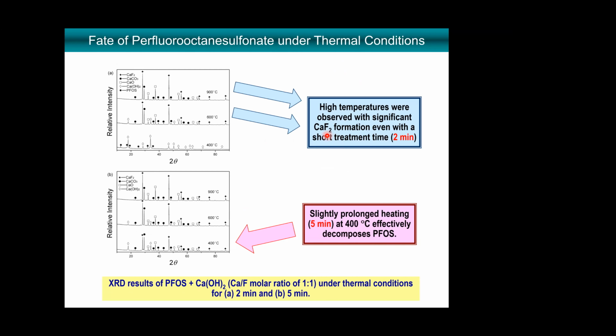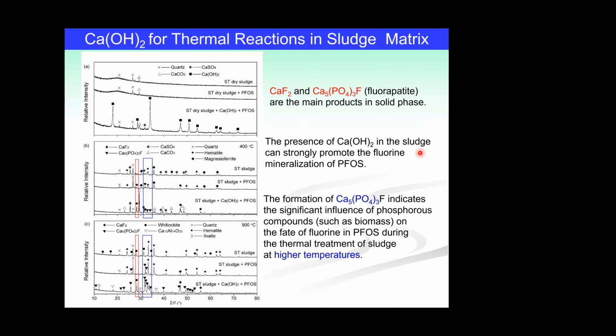If you can afford a little bit higher temperature, then in fact, say 600 or even up to incineration, 2 minutes will be enough overall. But when I say 2 minutes is enough, it means that you can actually reach it in less than 2 minutes. The reaction for the calcium fluoride formation is really fast.